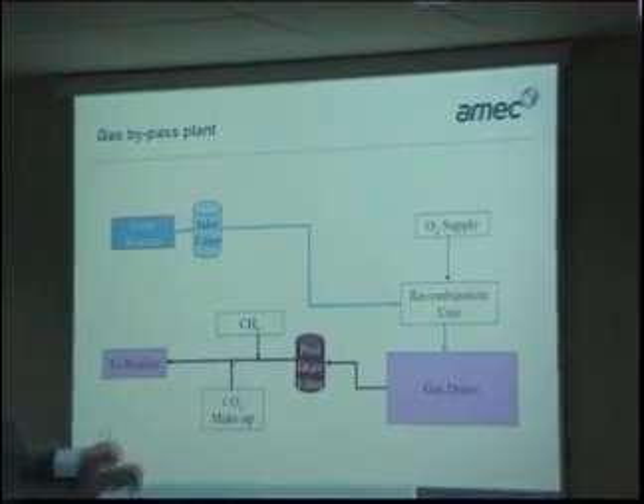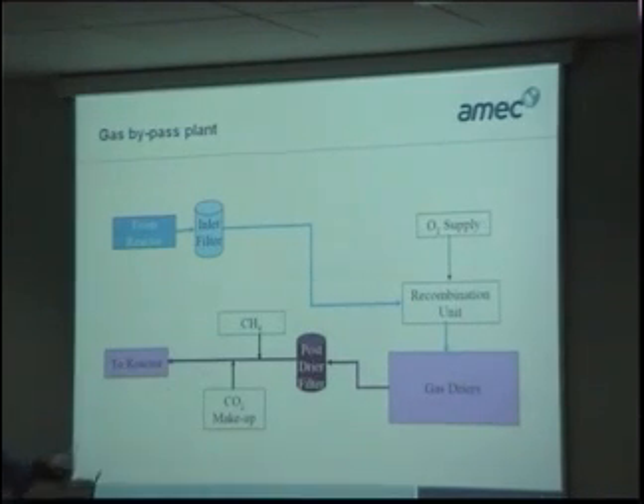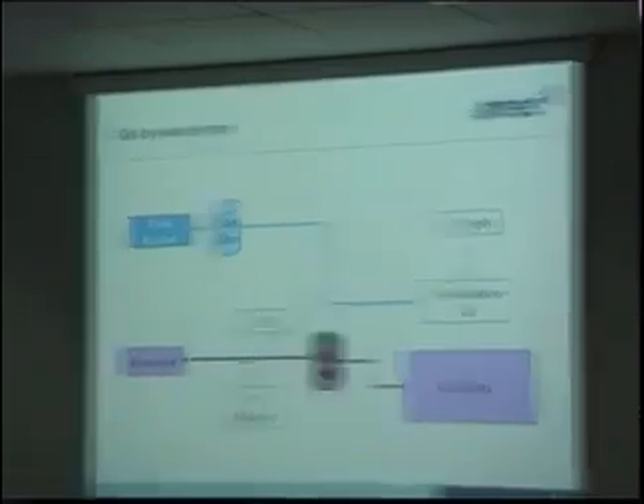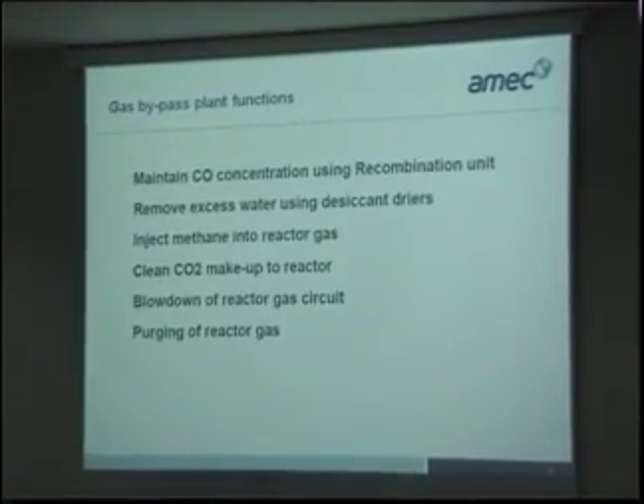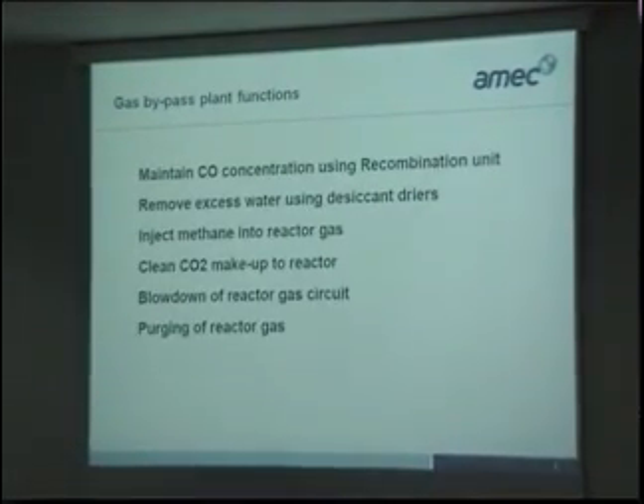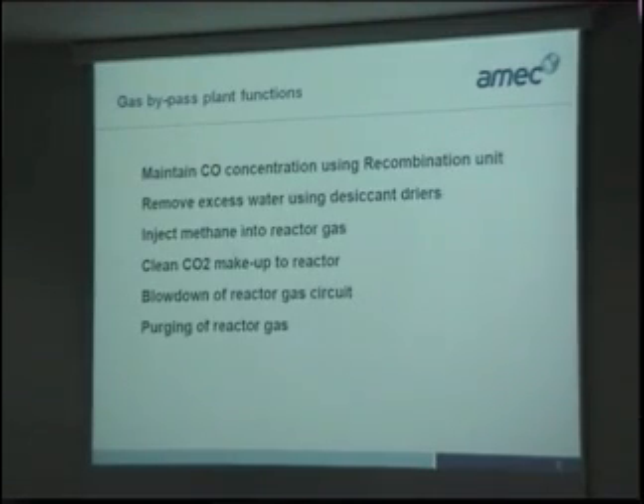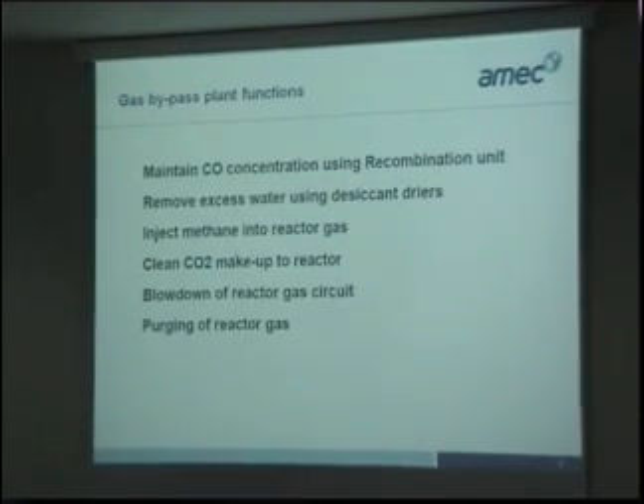A filter is put in at the back end of the dryers to prevent any desiccant fines, and here we have the methane injection for mopping up the oxidizing radicals, CO2 makeup if necessary, and then back to the reactor. So just to summarise the functions, we're trying to maintain a constant carbon monoxide concentration using the recombination unit. We're removing excess water using desiccants. We're injecting methane to mop up oxidizing free radicals, and then the other function is CO2 supply to the reactor. And if we want to blow down the circuit or purge the reactor, we do that via the gas bypass plant as well.